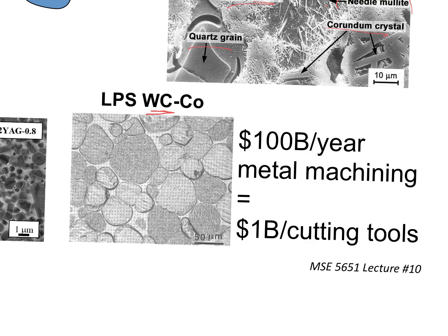And so what they do is they take tungsten carbide and mix it with cobalt, and you compact that into shapes. Remember, cobalt is nice and soft, so it kind of helps out in that area of things. And then you heat it up. What you've got here in this image is tungsten carbide particles with the cobalt liquid phase all around them. They've rounded out nicely, transport's occurring, and then you cool it off, and you have this really good tungsten carbide cobalt system that is used to make at least $1 billion a year in cutting tools.